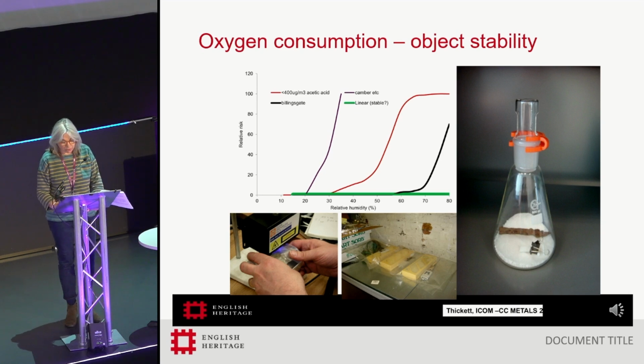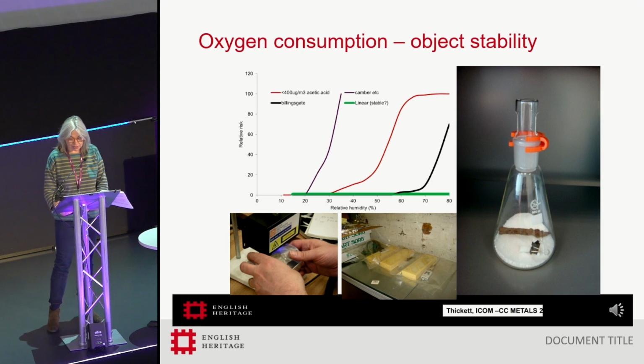If the iron and copper alloy objects tested show no oxygen consumption after 2 weeks, then we raise the RH to 75% for 3 days and test again. This allows us to display stable metalwork with organic materials at around 50% RH.